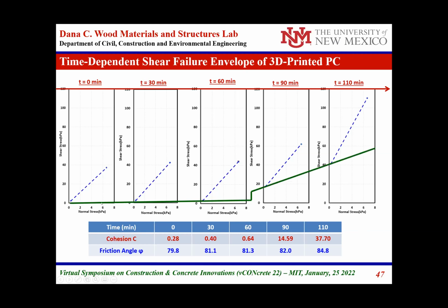You can see this is the cohesion of the material and how it changes with time. Some main changes happen between 60 and 90 minutes, where the material starts developing because the polymerization builds up higher. The interesting thing, because this is a polymer concrete, is that we can control when this happens. We can control the process of polymerization to make it happen a little earlier or later, based on the construction process and our interest in it.